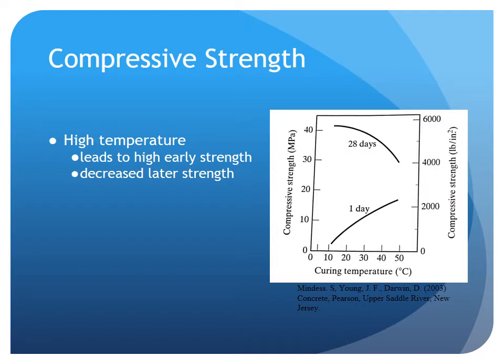Hydration is a chemical reaction in which compounds in cement form chemical bonds with water. The rate of hydration is directly proportional to the temperature, so the higher the temperature, the higher the rate of hydration will be. This attributes to the high early strength of concrete cured at higher temperature.